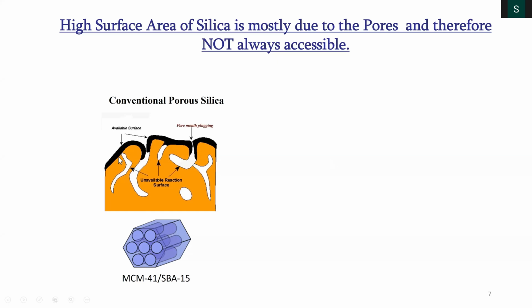Even with mesoporous materials like MCM-41 and SBA-15, which are names for porous silica materials, although they show excellent surface area because we measure the surface area using small nitrogen molecules, when you do catalysis in reality, as soon as you coat these surfaces with the active site, which is my next step, you start blocking the pores. So I'm ideally using a very small portion of the surface area and the remaining portion is not accessible. And then the reactant has to reach each of these active sites, which is also challenging.